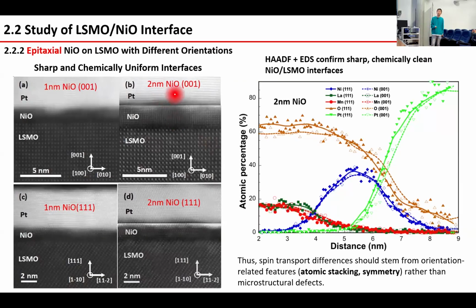Then we also add the 2 nanometer NiO on both orientations and measure the HAADF image. It shows that the NiO is quite distinctive, with a relatively clear and sharp interface as well. And also the EDS line profile across the 2 nanometer NiO on both orientations shows that the platinum penetrates a limited distance into the NiO, showing a continuous NiO film. And for both orientations, the elemental distribution is quite identical. So there's a quite similar chemical structure across the interface, regardless of the orientation. So the spin current transport difference should stem from orientation related features, such as atomic stacking symmetry, rather than microstructure defects.